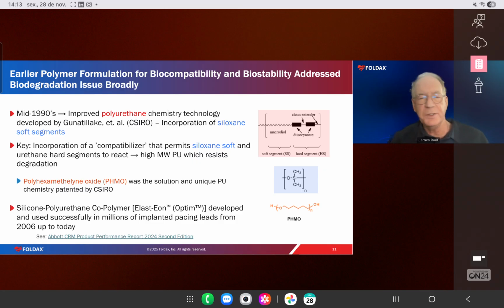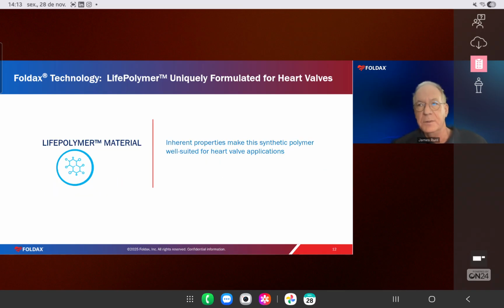And not all those breaches are polymer related. In fact, it's not clear that any of them are polymer related. So this material is really stable in a pretty aggressive biological environment. But this material is too stiff for heart valves. So what did we take away? We learned how we can connect siloxane segments with urethane segments using a compatibilizer, but we need to modify the chemistry further. So this is how Life Polymer came about.